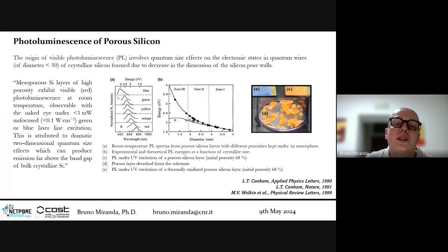So you can tune the dimension of these crystals by changing the way in which you perform the electrochemical etching. And he was able to obtain very strong photoluminescence under argon atmosphere, from red to blue, in all the conditions.